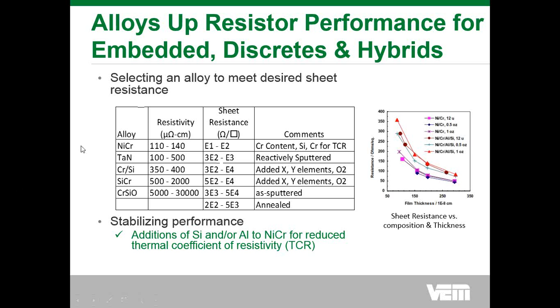So as Cynthia mentioned earlier in the talk, the first question is, I want a certain alloy, but can I sputter it? And so the question is, is it a conductive material? Metals and alloys are typically conductive and not really posing a challenge. Magnetic materials, if they're a metal or an alloy, yes, they're going to be conductive, but if you're doing magnetron sputtering, the problem is the magnetic nature of these materials may prevent the magnetic flux from escaping above the target so that you can maintain the plasma. So the question then is, what kind of thermomechanical processing do I need to do to these magnetic alloys to make the magnetic properties less so that I can get some of that magnetic flux from the magnets behind the target to go through the target and enable you to maintain a magnetron plasma.